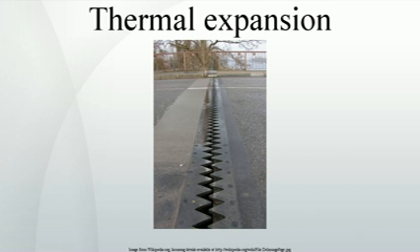Because glazes need to be firmly attached to the underlying porcelain, or other body type, their thermal expansion must be tuned to fit the body so that crazing or shivering do not occur. Good examples of products whose thermal expansion is the key to their success are Corningware and the spark plug. The thermal expansion of ceramic bodies can be controlled by firing to create crystalline species that will influence the overall expansion of the material in the desired direction.